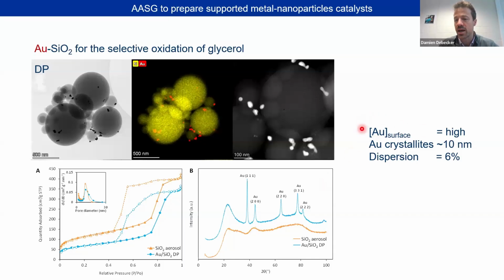If we analyze those by XPS, you see a concentration of gold that is relatively high. We can determine the size of the crystallites as being also quite large, 10 nanometers in that case, which is too big for the catalysis. And the dispersion, which we approach by a kind of titration technique with a mercapto molecule, is low. So, of course, this catalyst will not be very good for those reactions.